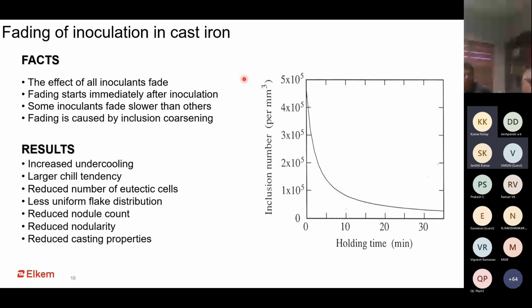When your inoculant fades, you have an increased undercooling. It means you have a poor graphitization. It means you also have a much higher tendency for carbides. It means that you have a reduction in the number of eutectic cells. You have a much lesser uniformity in the flake distribution in your gray iron. You have a much lower count of nodules in your ductile iron. And because you have a much lesser nodule count, your nodularity will also get affected.